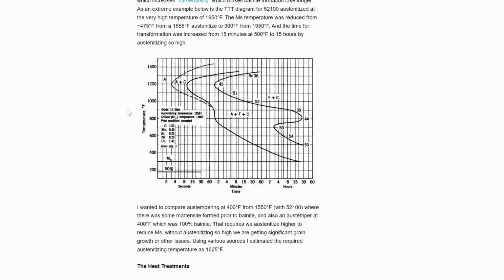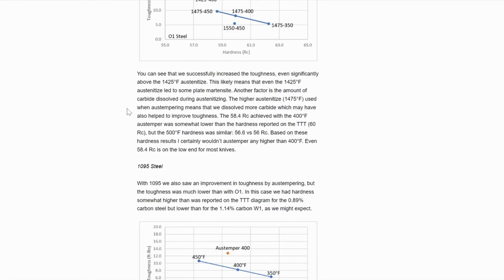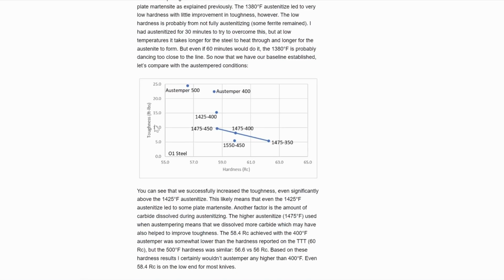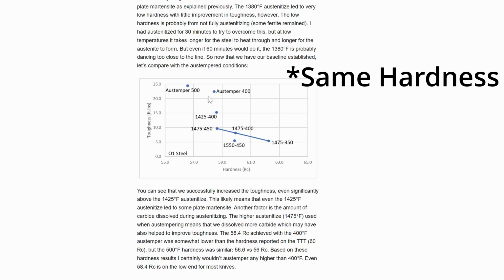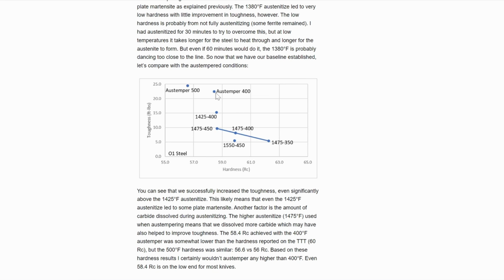And I have recreated some of these old tests. So here is a chart of O1. These are all quench and tempered down here. You can see that I maxed out around 15 foot-pounds with O1 when I used a relatively low austenitizing temperature of 1425 and tempered at 400. That gave me around 58.5 Rockwell. However, with the same Austempering treatment, I got over 20 foot-pounds. So a benefit of Austempering can be high toughness at intermediate hardness levels.